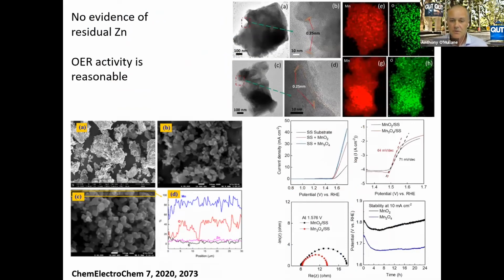In terms of its performance, it was reasonably good. Compared to commercial manganese dioxide, it was better in terms of the current density we're passing, and the impedance was lower during oxygen evolution. The most important part is that the stability was a lot better. For the commercial material, it started to degrade over a 24-hour period.